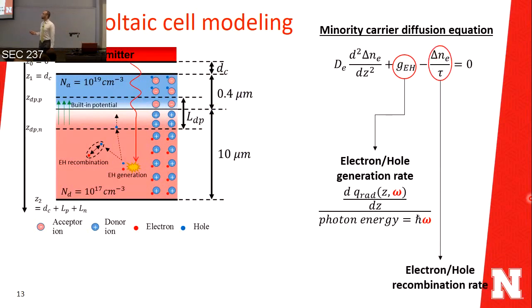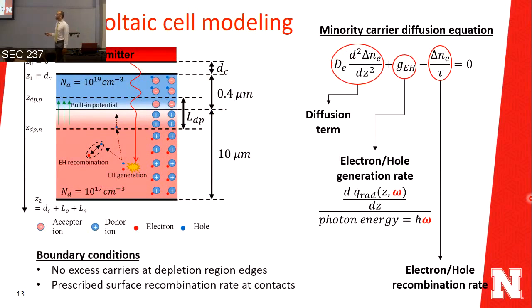You know, once you generate an electron hole, the electrons go to the depletion layer and pass to the other side to form the current. Unfortunately, not all of the electron holes generated participate in the current. Some of them recombine and annihilate each other, so they do not participate in the photocurrent. And the third term is the diffusion term. The boundary condition used here is that there is no excess carrier concentration at the depletion edges, and there is a prescribed recombination rate at the contacts.